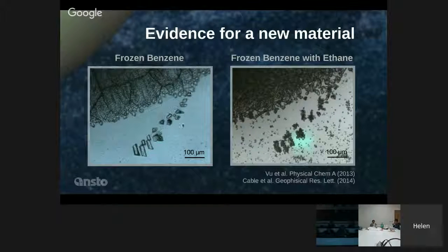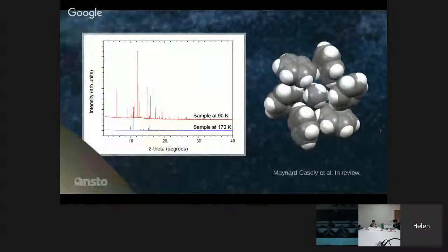Now, what the guys at JPL realized is that when you introduce liquid ethane, because ethane's liquid down to quite cold temperatures, you see there's quite a big change. The crystals pretty much all break up. They all get eaten up. They thought, well, hang on, something's happened here. Now, they didn't quite know what had happened. They'd started to look with a bit of spectroscopy, but what they really needed was some good old-fashioned diffraction to be able to tell them exactly where those atoms are. So they came to visit us here in Australia at the Australian Synchrotron, and we did that experiment.